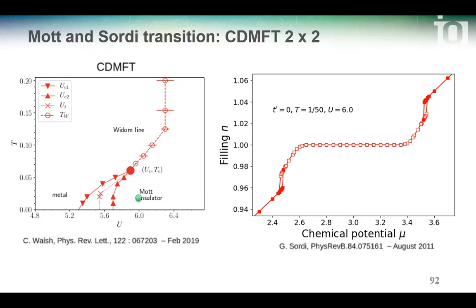So in the liquid-gas transition, what is the broken symmetry? If you map that to an Ising model, you can see an order parameter in terms of the magnetization. Here it's the same idea: if you map this to an Ising model, the magnetization becomes the order parameter, or here the difference in density is the order parameter. But strictly speaking, there's no broken symmetry. A liquid and a gas have the same symmetry. Because they're both gapless, as you said, you can't have a symmetry-breaking order parameter; if you're going between two gapless states, you can't have an Ising-like transition.